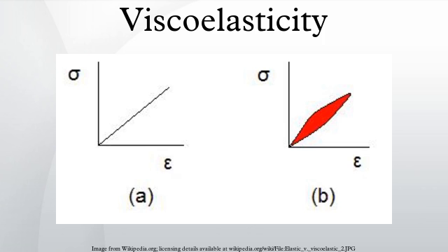When the stress is maintained for a shorter time period, the material undergoes an initial strain until a time, after which the strain immediately decreases, then gradually decreases at times to a residual strain. Viscoelastic creep data can be presented by plotting the creep modulus as a function of time. Below its critical stress, the viscoelastic creep modulus is independent of stress applied. A family of curves describing strain versus time response to various applied stress may be represented by a single viscoelastic creep modulus versus time curve if the applied stresses are below the material's critical stress value.